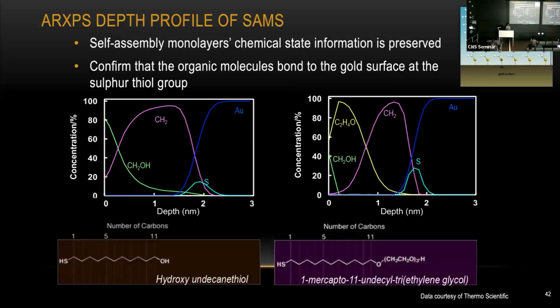And that's one dataset that was taken by Thermo Scientific a couple years ago. Again, the coating is a self-assembly coating. It's only about 2 or 3 nanometers. And for this one, you can't do depth profiling. Depth profiling is going to remove your coating right away, so you won't be able to see any difference. So the only thing you can try for this kind of measurement is tilting.